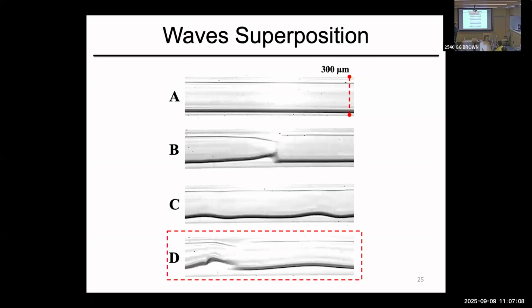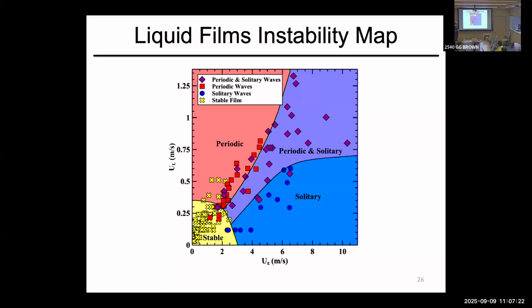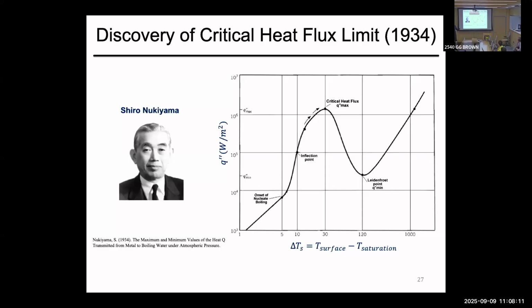So let's say in this case, what we figured out is that what is typically called churn flow is a superposition of these waves and this kind of wave, and I will tell you where it happens. So we had these periodic waves that happen at the higher liquid velocity, low gas velocity, that are mostly here. And then we have these sort of churn flow that people call in the flow boiling literature solitary wave. When you increase the gas velocity, it causes significant shear, and the fluid starts to churn and pick up from the main film flow. And if you're in between, you can have a combination. So that's what we had. And then if you're at sufficiently low velocity, then you have a basically stable flow.